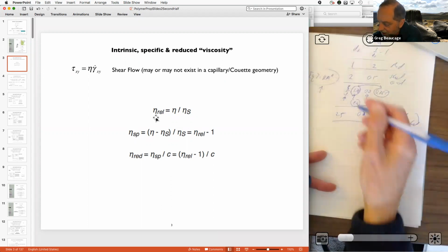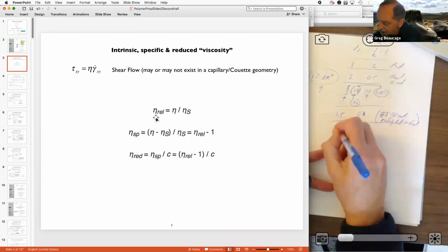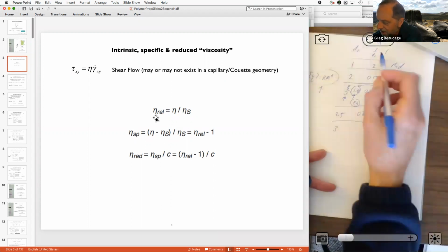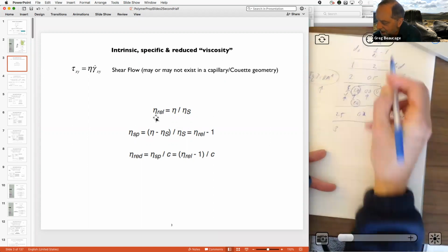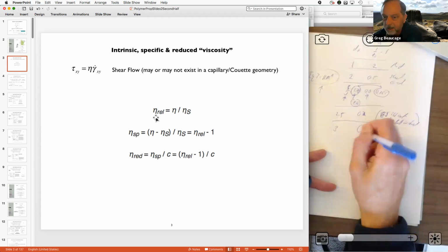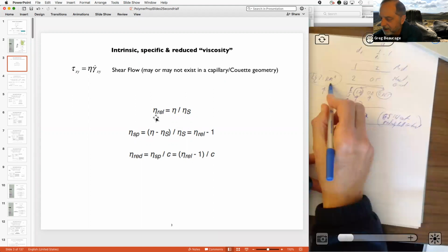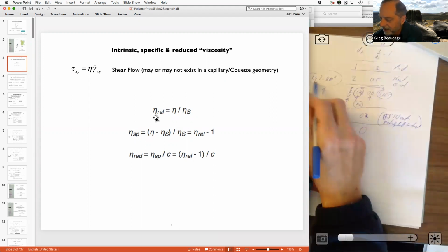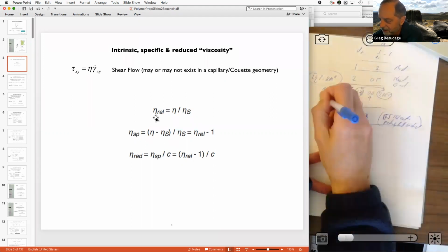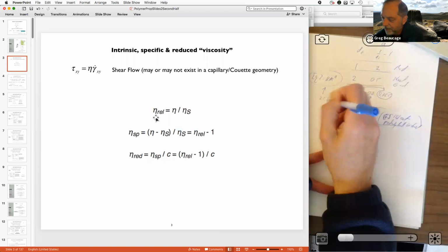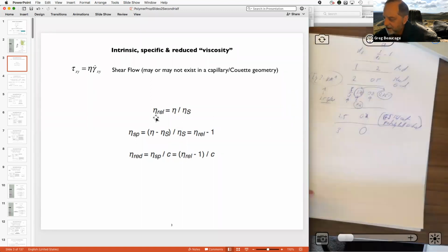And if it's 3D, then 3 by 3 is 1, minus 1 is 0. So this a number is 0, and it doesn't depend on molecular weight. M to the 0 is 1, so you just have a fixed value. Then that K is 2.5 for a sphere. Right, so you can kind of map out what you can get.